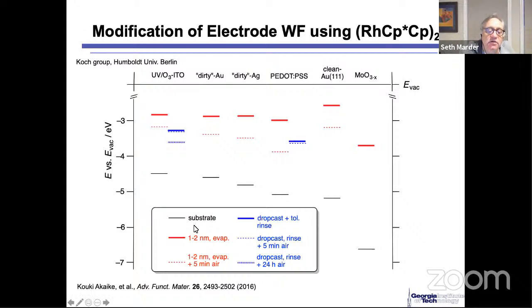And then they do 2 experiments. One, they measure the work function. Two, they let it sit in air for 5 minutes. And then on the solution ones, they let it sit in air for 5 minutes, and then 24 hours.